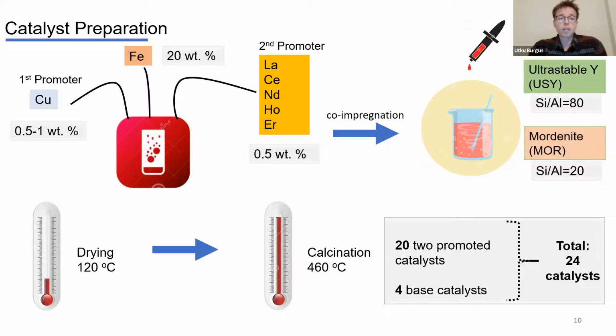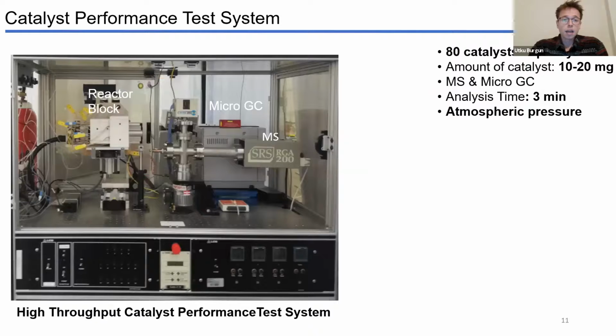At first, all metal precursors were dissolved in deionized water, and that solution was then co-impregnated onto our zeolite supports, which are the ultra-stable Y with a high silica-alumina ratio and mordenite support with a low silica-alumina ratio. And after the drying and calcination processes, a total of 24 catalysts, which comprised 20 promoted catalysts and 4 base catalysts, were obtained.